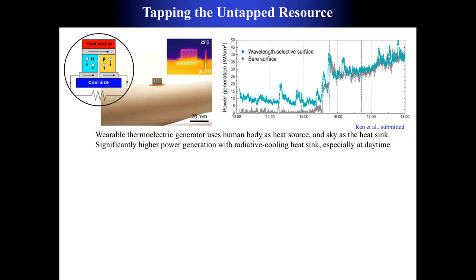Now, unfortunately, any time you have thermoelectric generators and you wear them like what I show in the picture, there is no heat sink during the daytime, because the sun sheds a lot of energy on top of that and makes it hot. In the picture, you see very low power generation during daytime. But if you use radiative cooling material, you can get good power generation in the daytime. That's one thing to look into, really changing the heat sink, following a similar line to what I mentioned in the last slide.